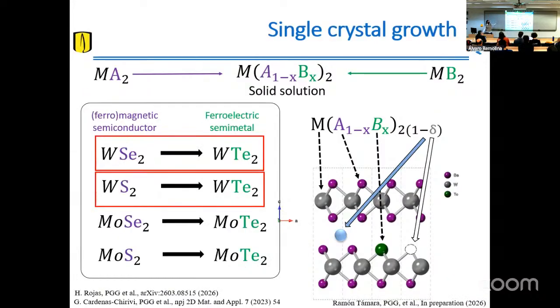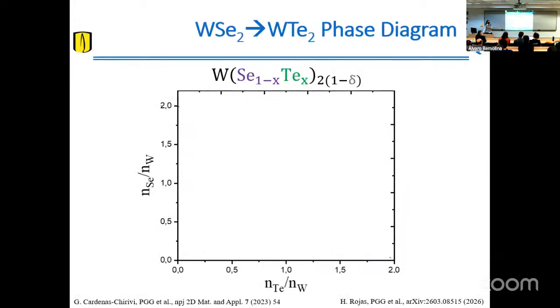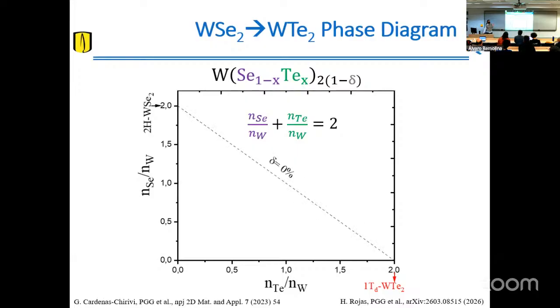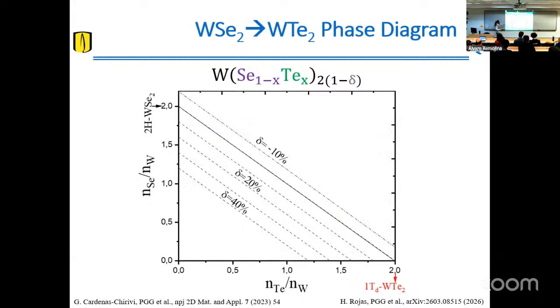We have studied these specific mixtures of these compounds, and I'm going to go really fast because time is almost up. So we summarize our results in this phase diagram. We plot here the amount of selenium relative to tungsten and the amount of tellurium relative to tungsten in this specific mixture. The stoichiometric compound with no defects has this formula, which we can represent in this diagram by this line. So the compound with no defects at all, just replacing selenium by tellurium, goes along this line. As we increase x, the amount of tellurium in the compound, we move along this line, and different amounts of defects can be represented by parallel lines like this in the phase diagram.